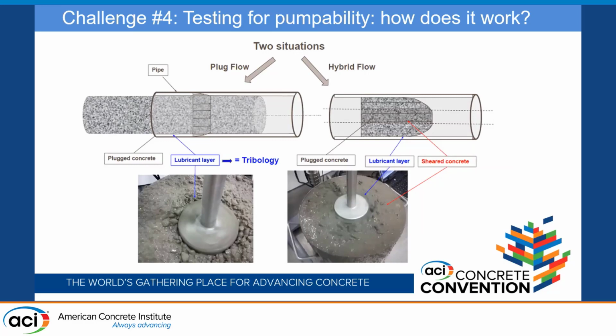There's a video here in a short bit that shows you this, but what you see as it starts turning, like this right here on the left, is what we call a plug flow. This would be traditional concrete. As it starts turning, you get a slight lubrication layer between the shaft and the concrete, and that lubrication layer is what helps the concrete push in the pump. As you see on the top, the majority of the inside of that concrete is plugged. It's not plugged in the pump, it's just a plug, and you're pushing it with the lubrication layer.